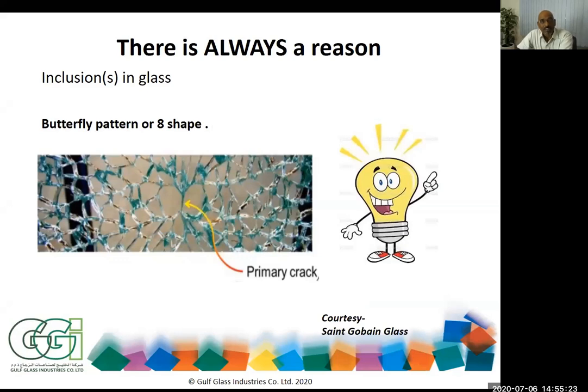Butterfly pattern or 8 shape. Many people in the industry look at the glass and they say, wow, that's a butterfly pattern, that's an 8 shape. And eureka, they have found it. Oh, this is spontaneous breakage, this is nickel sulfide breakage. That is not the right approach. Everything that has a butterfly pattern does not indicate that it is an inclusion breakage or nickel sulfide breakage, because glass can break due to concentrated load as well.